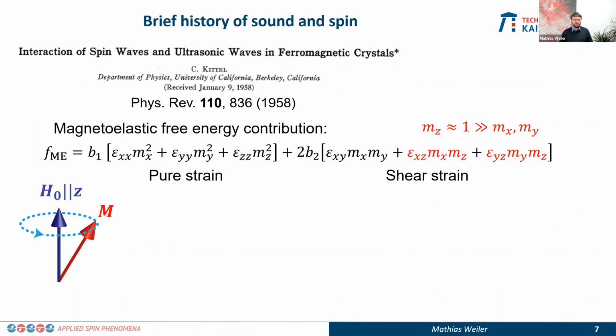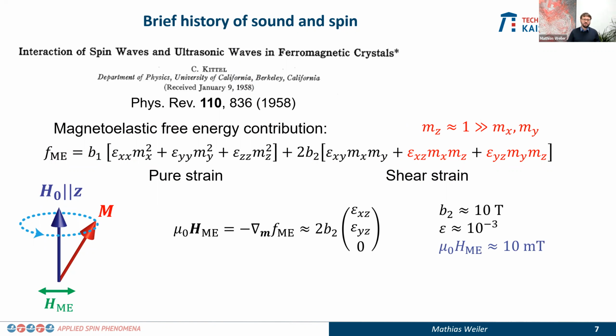And in this theory work, what Kittel introduced was the magneto-elastic free energy contribution, where one can see that a pure strain and also a shear strain modify the free energy density of such a thin film, because either pure or shear strains modify the magnetic anisotropy of the material. And that is due to spin-orbit interaction. One can then derive, as Kittel already wrote, from the free energy an effective field. So it's the magneto-elastic effective field, and that's the derivative of this free energy with respect to the magnetization direction.